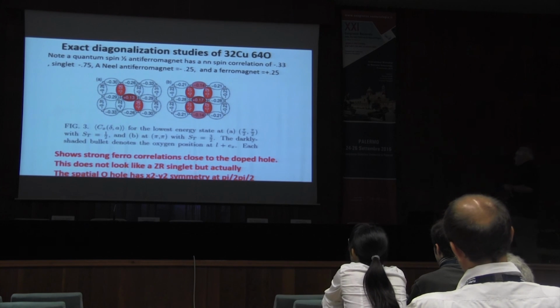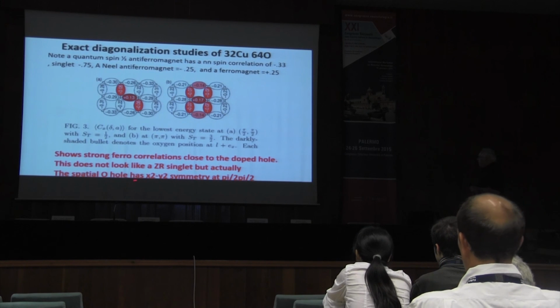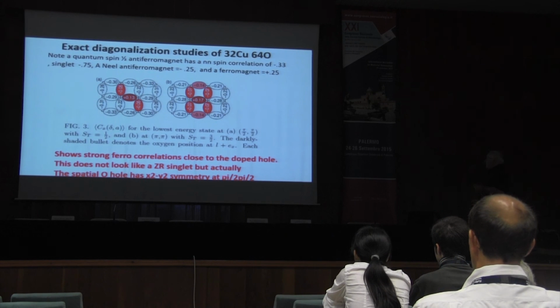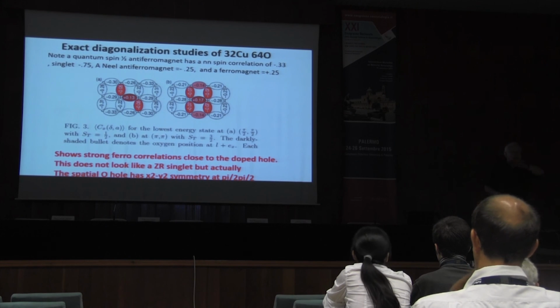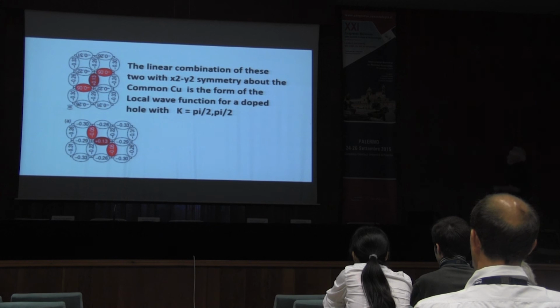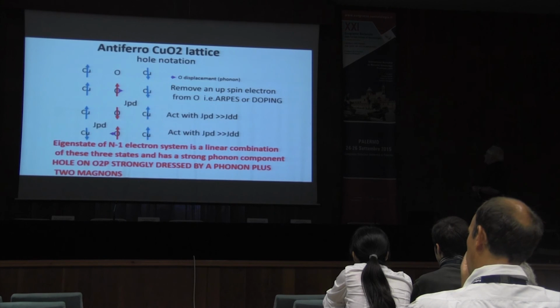This does not look like a Zhang-Rice singlet, but actually the spatial hole has x squared minus y squared symmetry nonetheless, because you can make a linear combination of the hole here and the hole there if you are in diagonal k vector here. Okay? And they actually have x squared minus y squared symmetry. So it looks like you have an Emery-Reiter three-spin polaron in a Zhang-Rice-like symmetry. So they're both right. Okay? And I just drew that picture over here just to show you that symmetry.